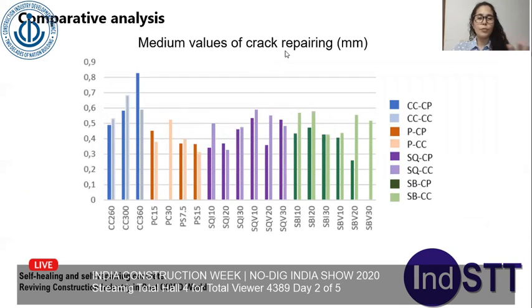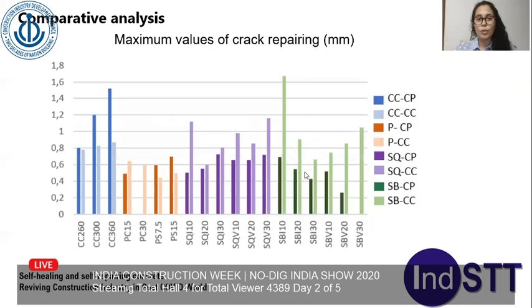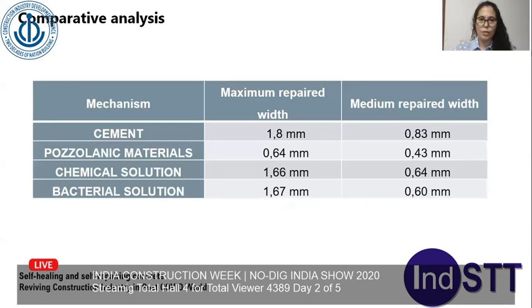When we check the medium values for crack repair, we may think that cement consumption was the best option, which is not, because there are just a few occurrences. That's why the medium value is bigger than in the others. We can see the good behavior from chemical and bacterial solution. And for the maximum values, we reached values above 1.6 millimeters for bacterial solution, which is really good considering the real cracks in structures.